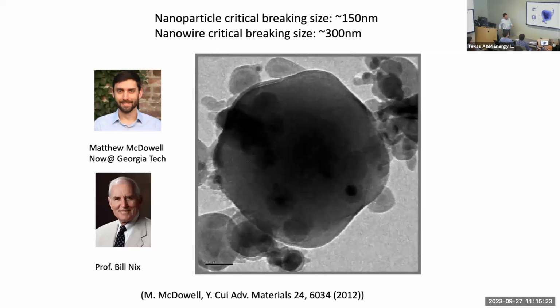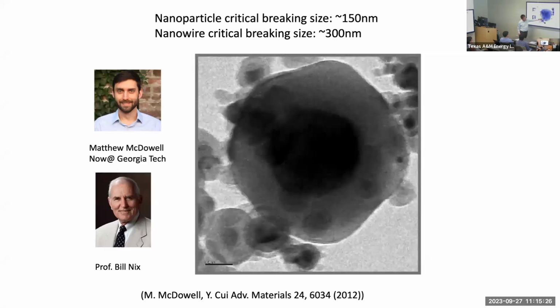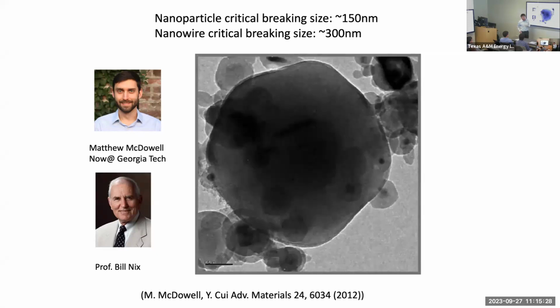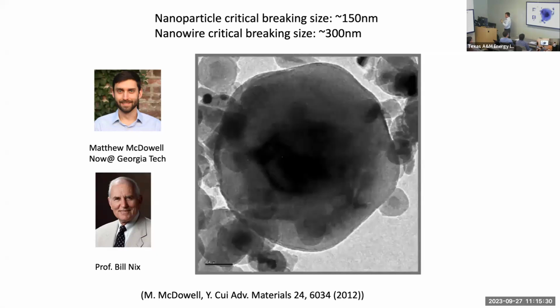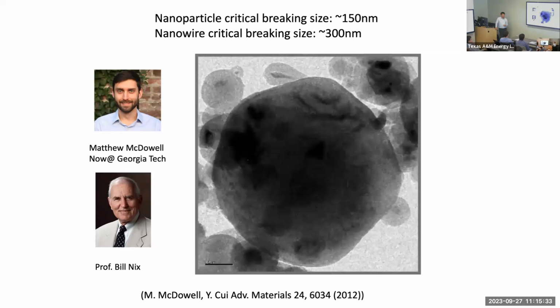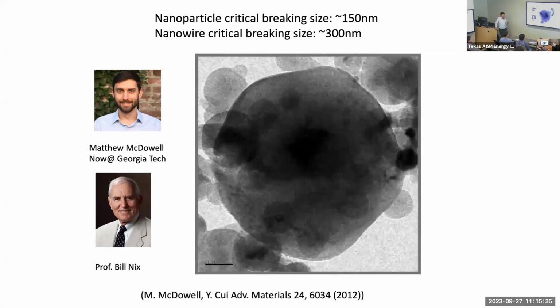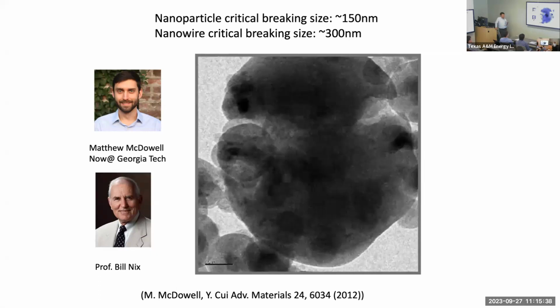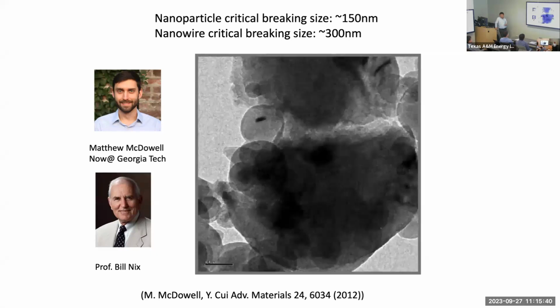Now lithium is coming in and makes lithium with silicon become an amorphous alloy. You see this crystalline core keep shrinking. These particles just keep expanding until the stress is so big, and then it cannot take any more. You see this particle is broken. Once it's broken, this material is no longer connected with each other, so your battery's capacity will just decay so fast. The first cycle, you build a battery, you charge it up, and the battery has already died.